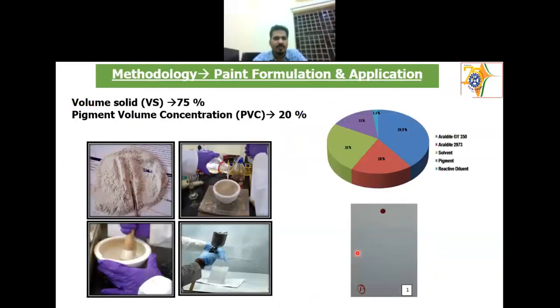And then the coating we made, and this is the pigment, including the Pani pigment. In a typical coating, we'll have many other pigments also. I don't know how many of you are into paint formulation. For a paint formulator, there are some values, like the volume solid and pigment volume concentration. Simply, I would say the volume solid is the total solid content of the coating. That means 75 volume solid means the remaining 25 is solvent.